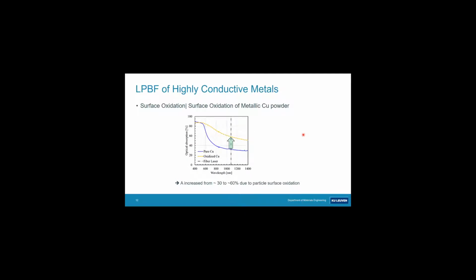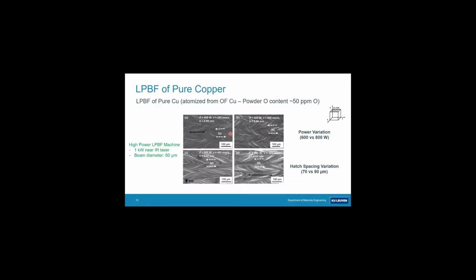When looking at powder, it's fairly easy to increase its optical absorption. So you see here a comparison between absorption curves between pure copper and oxidized copper powder. And you see that in the powder state, of course, at the near infrared laser wavelength, there is a clear increase in absorption behavior. If the laser would shine only on powder, this would probably provide a solution. But the question still is, what will happen once everything is converted into a melt and your laser shines on the melt pool? One way to do it is, of course, to introduce roughness and impurities at the powder surface.